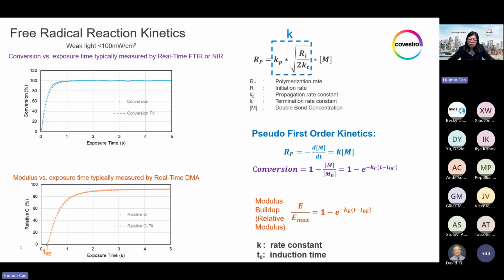The pseudo first-order model is not just empirical. It is actually well-founded by theoretical kinetic models, such as this most commonly used reaction diffusion model. And this model assumes a steady-state propagation process where all these parameters are constants, which are combined into one overall rate constant K. And for double bond conversion, this would be Kc.